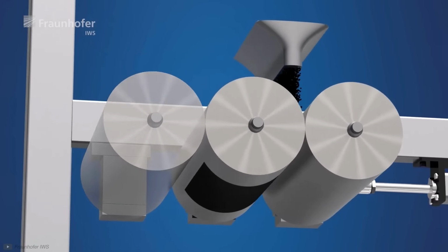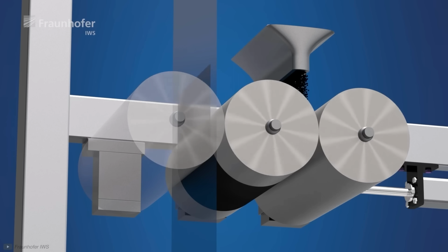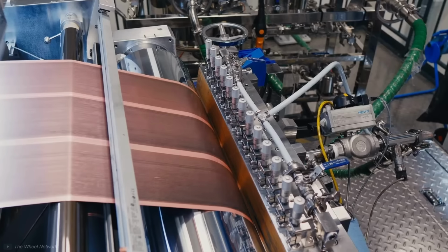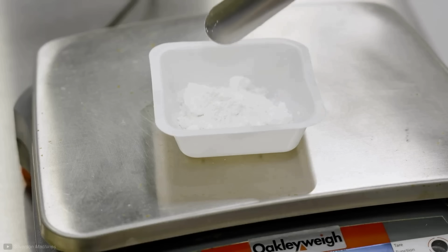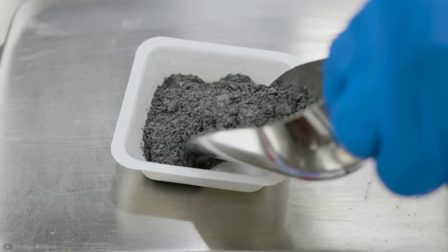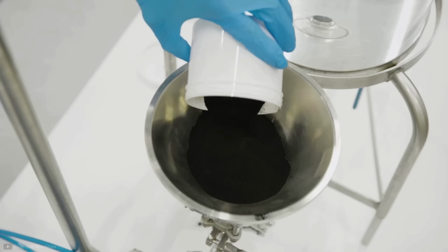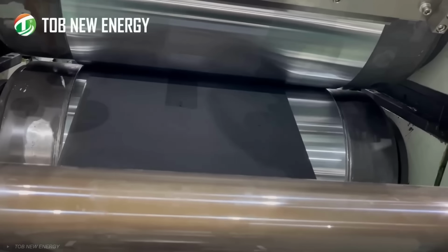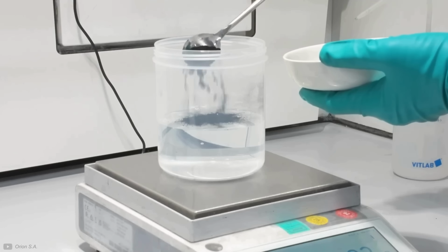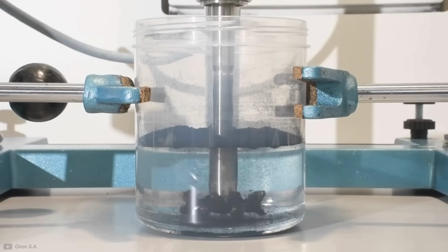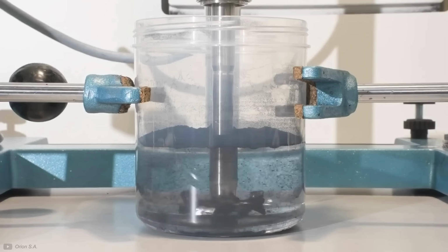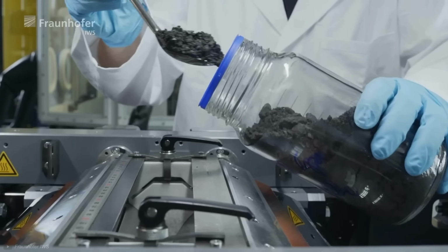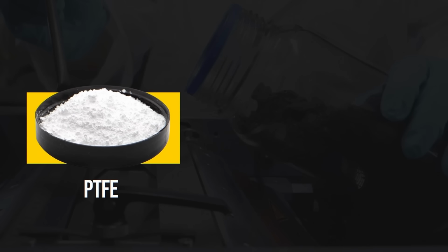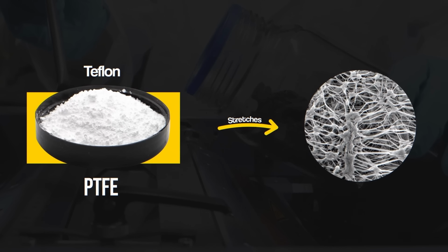There is a challenge though. Dry electrode powders don't stick to the current collectors as easily. This is where one of the big innovations is used, and it allows the electrode powders to stick to the current collectors. Instead of using a liquid and a dissolvable binder material to stick everything together, the dry process uses a special polymer, usually PTFE, which you might know better as Teflon, and physically stretches it into tiny fibers.